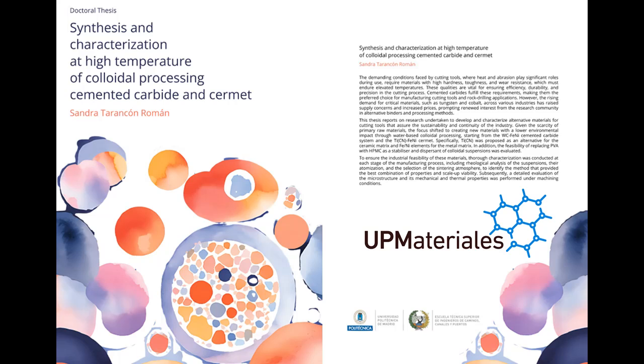They are. But on a positive note, the new materials showed good tribological performance. Lower friction at 25 degrees Celsius compared to the reference. So a mixed bag, but some promising results overall. And it sounds like they developed a very sophisticated process for creating these materials. They did. They successfully made tungsten carbide iron nickel and titanium carbonitride iron nickel composites using colloidal processing and optimized sintering. It's a real testament to the power of material science.